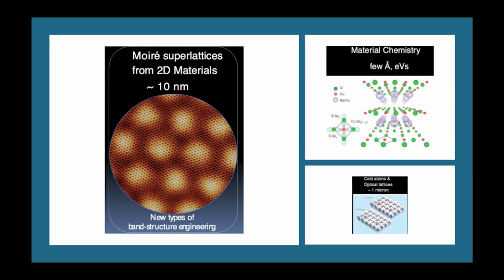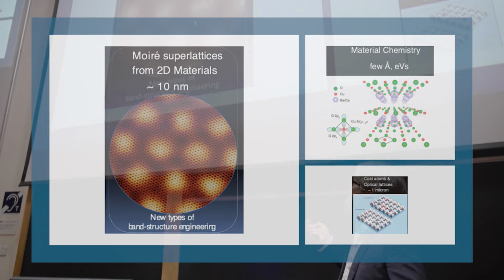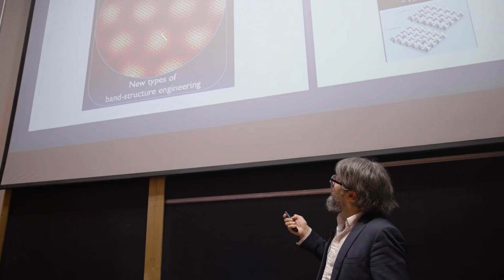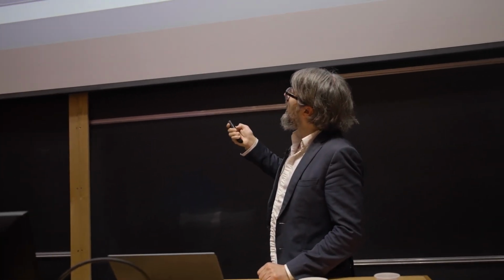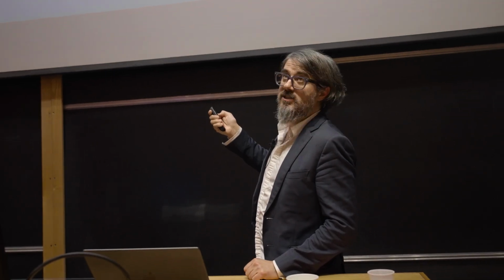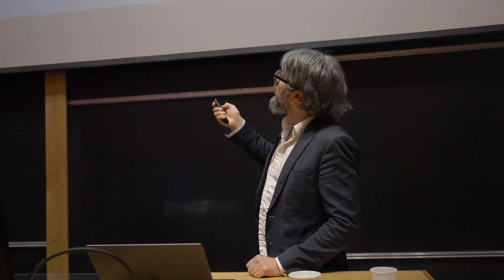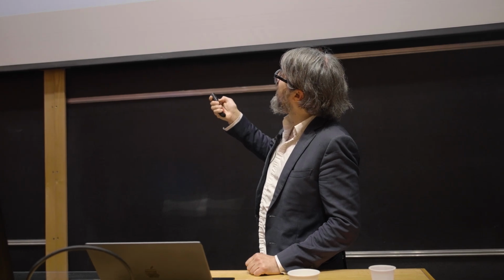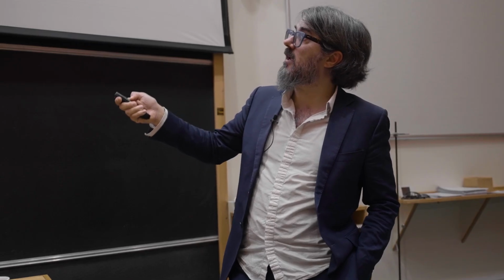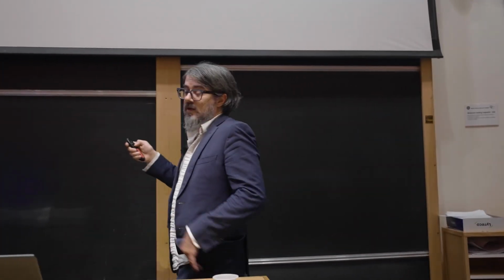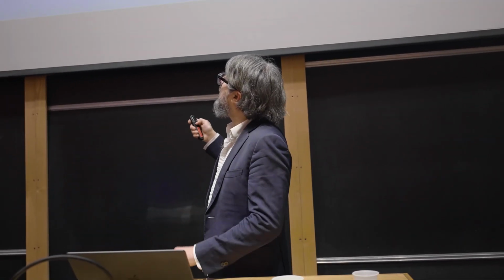So for example, this is the twisted bilayer graphene, which is what Pablo Jarillo-Herrero was probably talking about here a few years ago. This method was invented by Emanuel Tutuç, but basically what it does is it controllably takes 2 layers of graphene, and you can see the initial lattices of graphene that are these small unit cells here, and it rotates them by a small angle. And you can see what happens is that now you have a super periodicity at a much larger length scale. This length scale is of the order of nanometers or tens of nanometers, basically 10, 20, 30 times the original lattice.